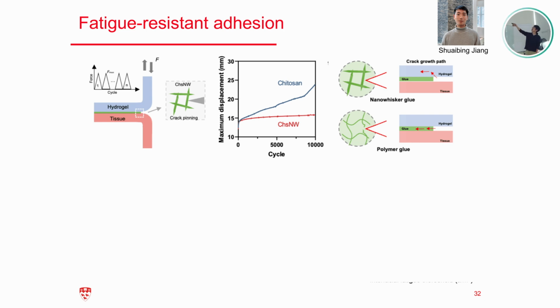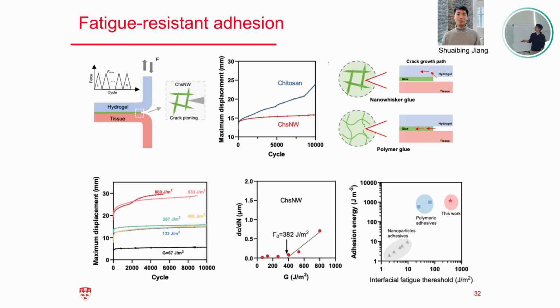But in the case of the very rigid nanocrystal nanowhiskers, this crack will be pinned by this very rigid material. And since the gel matrix is softer, naturally the crack will try to go over and kink into the hydrogel matrix. So that is a mechanism to stop the interfacial crack propagation.